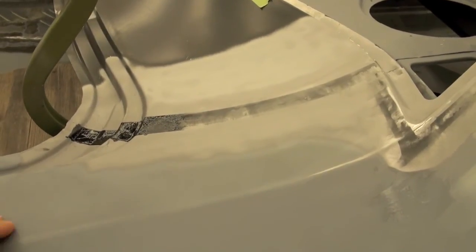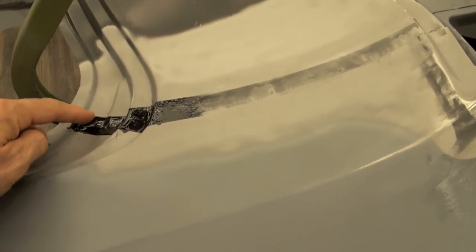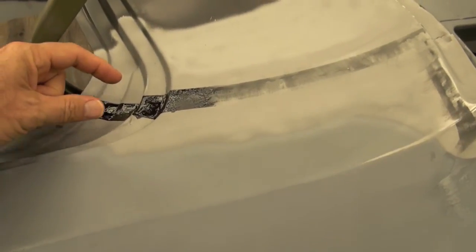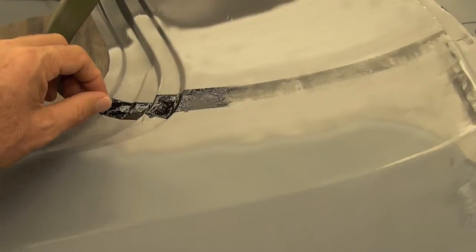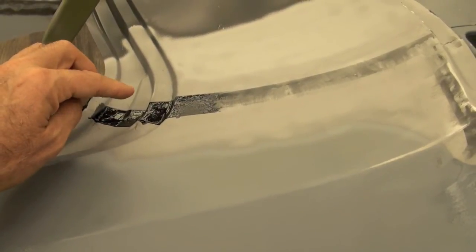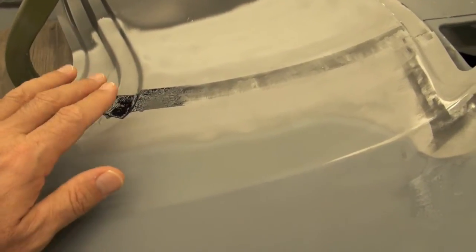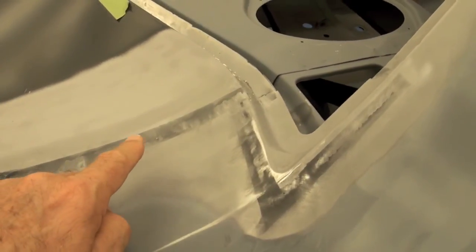Then you take 3M's 8511 and you tape off, put a little bit of coating in any little pits or any imperfections that you would have in the welds. Then let that dry and sand it down to almost nothing.